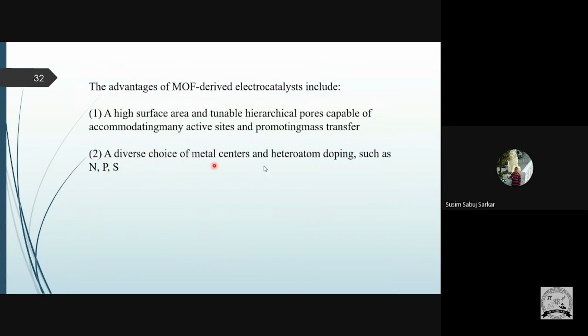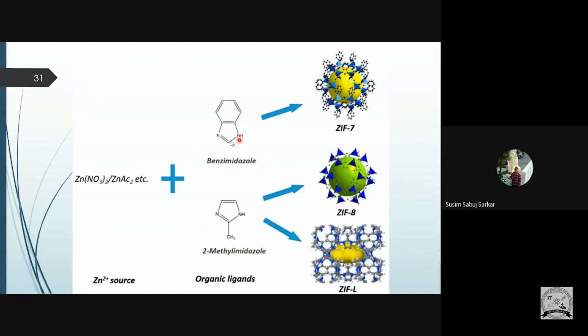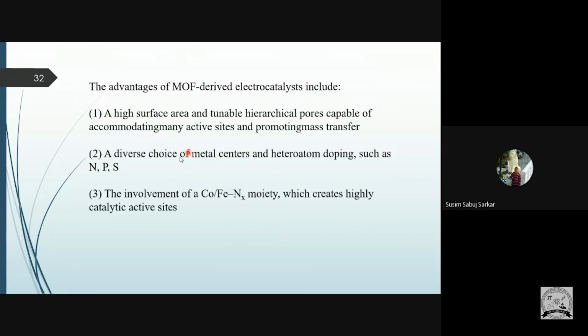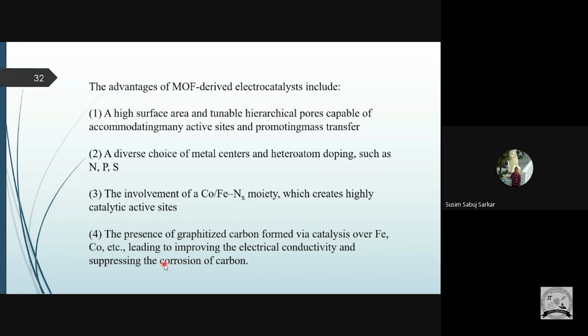And the second is the diverse choice of heteroatoms and doping. Not only can we use this metal source, we can also dope with other metals. In the organic linker, that means the organic ligand, we can dope with nitrogen, mainly, and also phosphorus, sulfur and other things. So this also helps us, and also the involvement of the CoFe-N-x moiety, which creates highly catalytic activity, and the presence of graphitized carbon formed via catalysis over Fe, Co etc., leading to improved electrical conductivity and suppressing corrosion of the carbon.